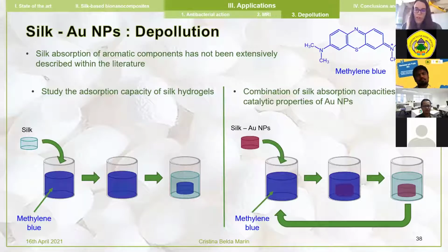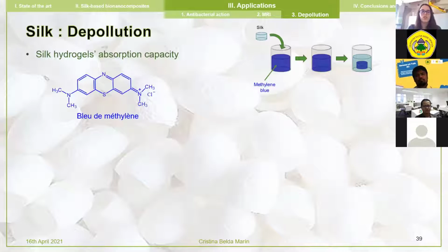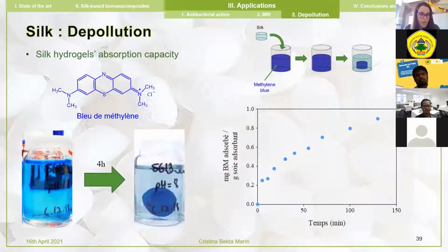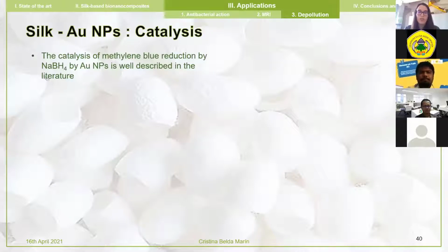So let's start with the first, the characterization of the silk hydrogel's absorption capacity. As you can see from the image, when introducing our hydrogel into a methylene blue solution, over time the quantity of methylene blue absorbed by the hydrogel increases until the time where no more methylene blue is contained within the solution. As you can see here at the beginning, the hydrogel is in the solution, but we cannot see it. At the end, it is blue because it has absorbed all the colorant. So now we want to combine this property of absorption with the catalysis of gold nanoparticles.